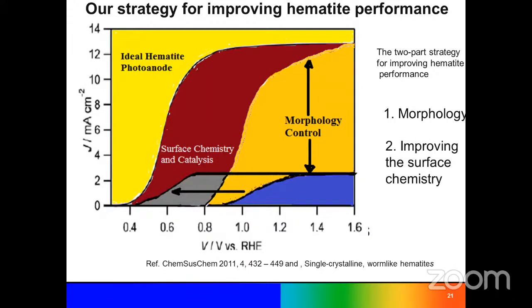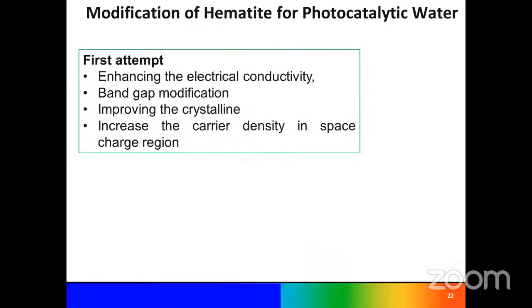The surface state: if we coat with different photoresponse materials on the surface, like perovskite material, then the surface chemistry will be changed, and then the photoabsorption property will be very high. Then the minimum requirement of voltage will also be less, and it will reach the theoretical value of around 0.4 volt.